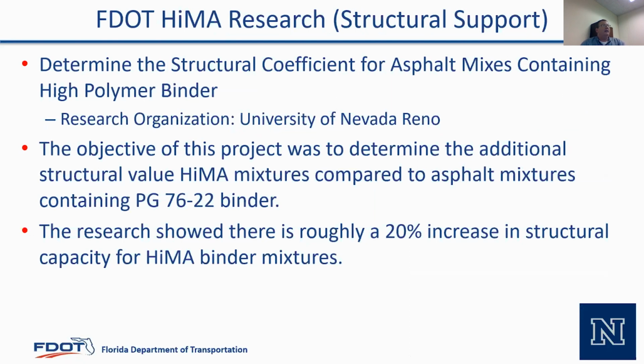And again, they looked at comparing our conventional mix with a polymer modified PG 76-22 binder and taking a comparable HiMA mix and comparing the structural resistance, or basically the structural support between the two mixes. They've got a nice facility out there. And what the research essentially showed was there's about a roughly 20% increase in the structural capacity of the HiMA binder mixes. To put it in layman's terms, in Florida, we give all our mixtures a structural coefficient of 0.44. That's what we do. We're still an AASHTO 93 state. And again, what they determined was, through all their extensive testing, both with respect to bottom-up cracking, rutting, whatever, you could increase that structural coefficient to a 0.54 very conservatively. So again, you get that increased structural support that you're looking for.